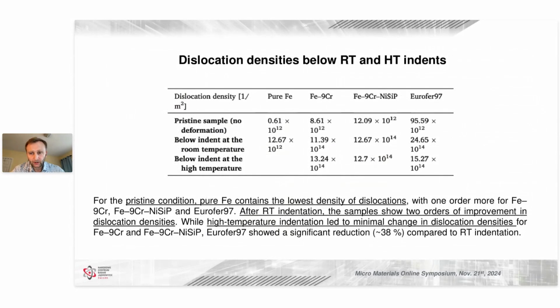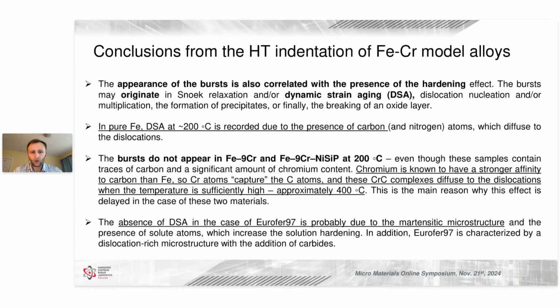So the next step was to calculate the dislocation density, and obviously there is a huge difference between non-deformed and deformed material at room temperature in the dislocation density below the indent. However, we did not see a huge increase of dislocation density after high temperature indentation. Moreover, Eurofer 97 showed a significant reduction, by almost 40%, in dislocation density compared to the measurements done at room temperature.